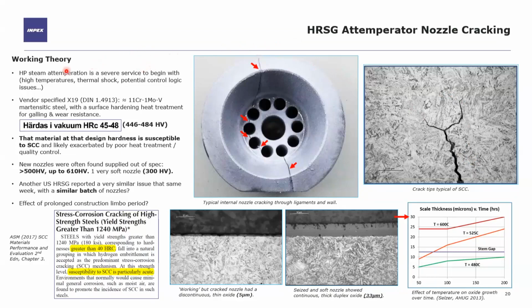So the vendor has specified an 11% chromium martensitic steel, in some ways not too dissimilar from P91, with a surface hardening treatment to improve the galling wear resistance. And they targeted a 45 to 48 Rockwell C range, which is about 450 to 480 Vickers. That might have been reasonable for those 2 characteristics. However, it is quite well known among metallurgists and in some fairly important books that these sorts of materials, at these sorts of hardnesses, are acutely susceptible to stress corrosion cracking, theoretically even in moist air.